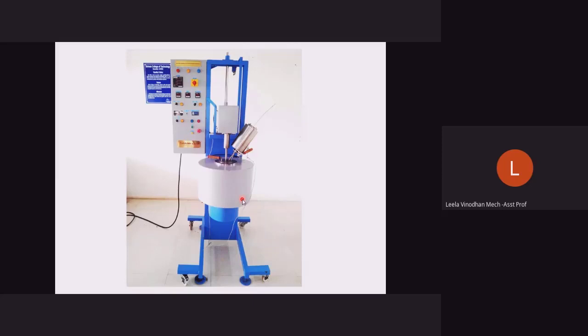We may think that we have taken it to a dry condition, but we also explore in those areas if you are keeping the reinforcement at a higher temperature, like 500 degrees Celsius or 550 degrees Celsius for 10 minutes or 15 minutes, even if you keep it for 1 hour and then introduce that into the stir casting, then that is definitely going to give us a different result. There are so many papers which have touched upon the parameters we have discussed today. So you can try in these aspects also. There is a lot of scope for this.